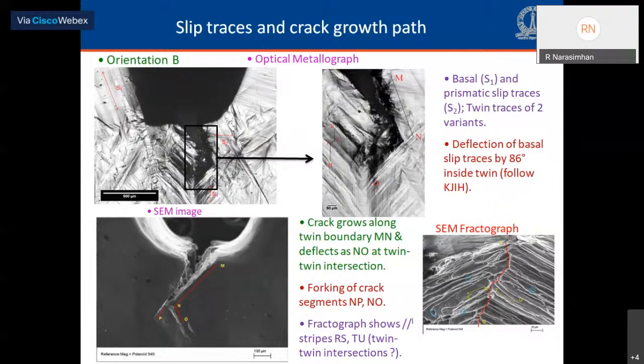If you look at the left side image, the optical micrograph, we can make out two slip traces, S1 and S2, which I have marked. The S1 slip trace, which is parallel to the notch flank, pertains to basal slip. The S2 slip trace, which you can see near the extended crack, which are horizontal, pertain to prismatic slip. Also, you can see traces of two twin variants, which are intersecting ahead of the crack tip.